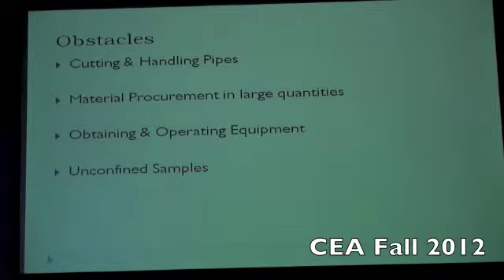For the unconfined samples, we're doing plain concrete samples. As molds, we proposed to use PVC, but cut vertically. The problem with this, when we were casting the 30 centimeter specimen, was that the concrete had cracks, because the molds were cut vertically. The concrete is supposed to be stuck to the plastic when it expands, but since the plastic is cut, it didn't provide good enough support for the specimen.